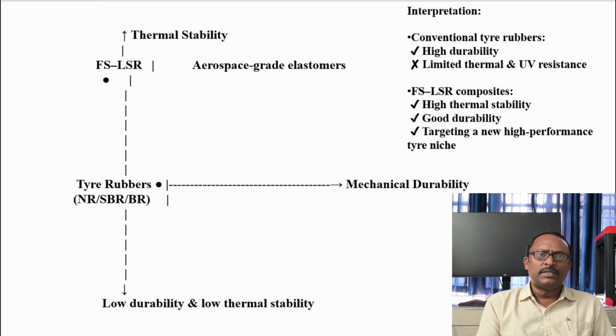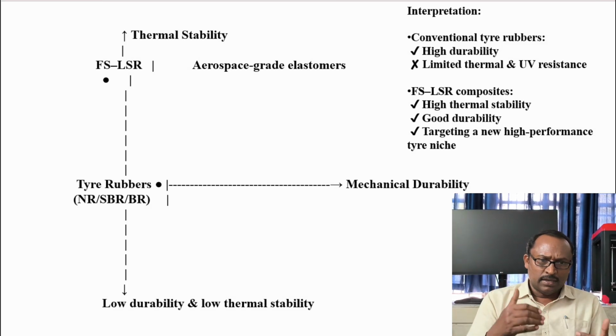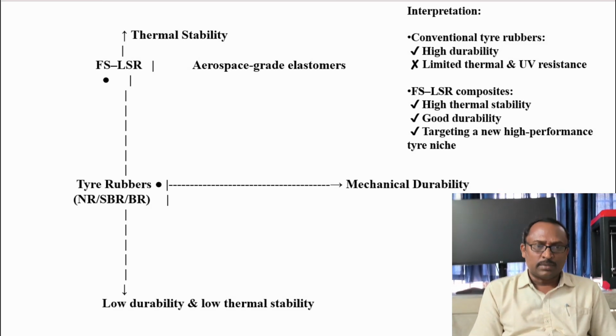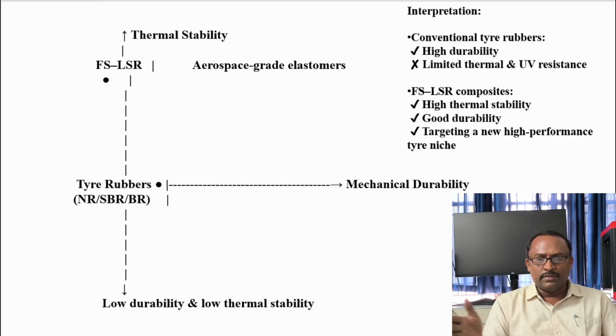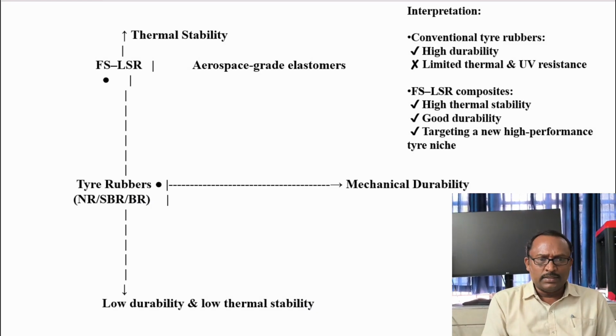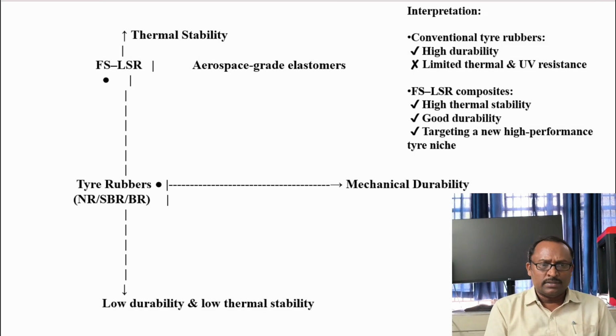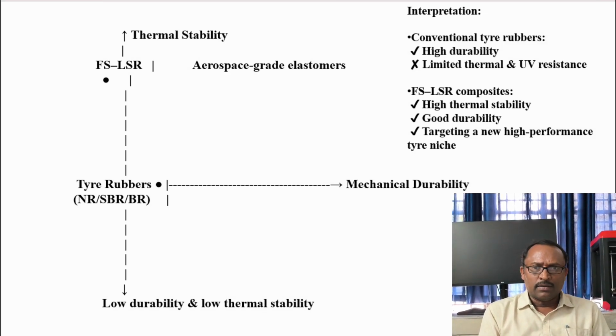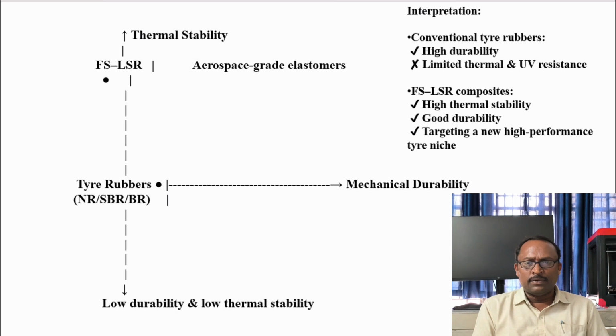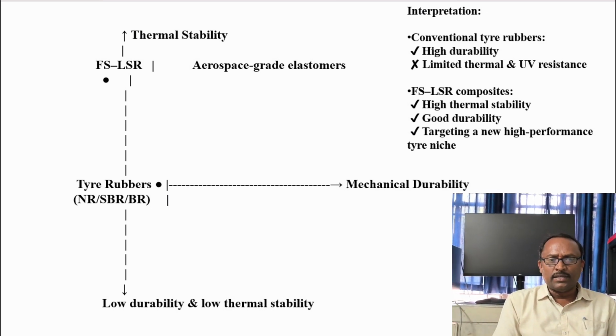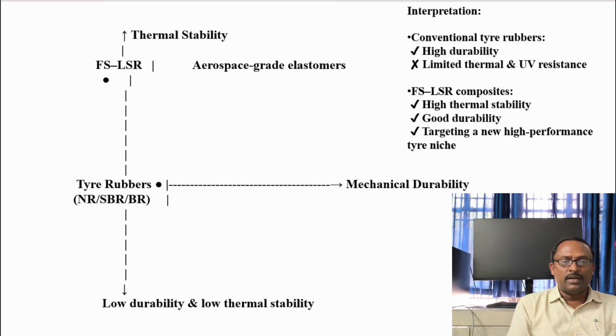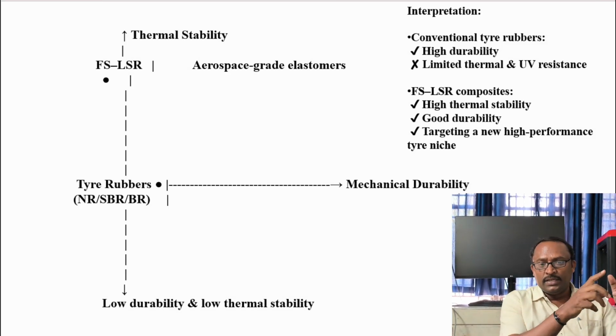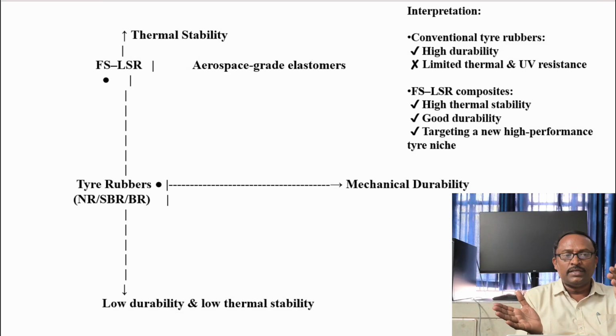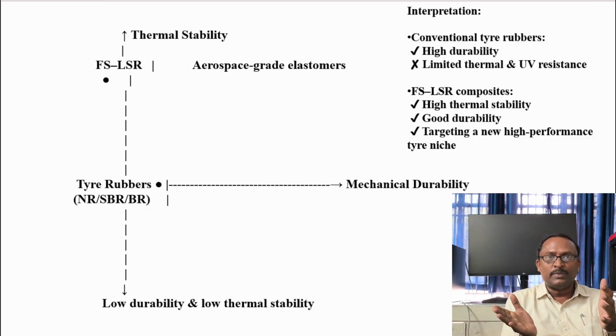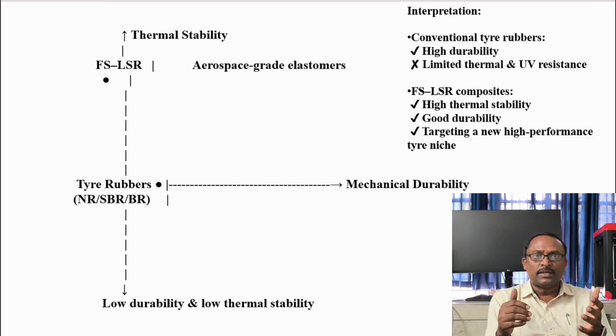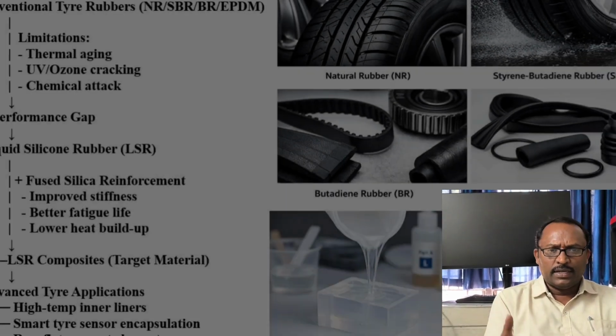So the required basic things are thermal stability on one side, and on the other side low durability and low thermal stability, and on the right side you can see mechanical durability. For this, NR is natural rubber, and this is a silicone based rubber, and a different rubber, filler reinforced materials were used. The interpretation is here. If you want aerospace grade elastomers, you need higher thermal stability as well as mechanical durability. This combination you have to design for the tire material by using the fused silica reinforced liquid silicone rubber. You can see the diagram very clearly.